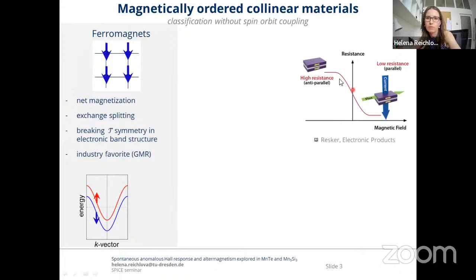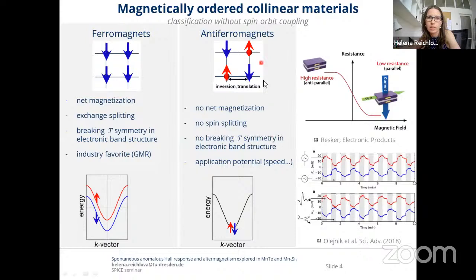The second large group of materials are the antiferromagnets, and the antiferromagnets are characterized by the alternating spin up and down in these individual sublattices. Therefore, the total net magnetization is zero. They do not have net magnetization outside. And they also exhibit no spin splitting in our non-relativistic classification. And they have no breaking of the time reversal symmetry in the band structure.